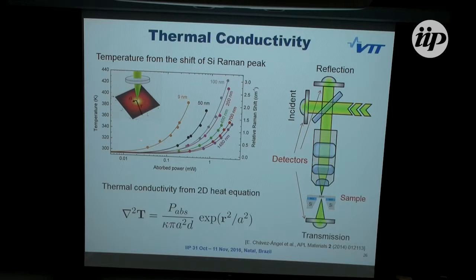So here are the measured curves. These are different thicknesses of membranes. When the absorbed power is increased, the temperature increases, so there's a shift of the Raman peak. And these curves can then be fitted with this 2D heat equation, where A is the spot size, R is the coordinate, and D is the thickness of the membrane. And this we know now, so we can calculate the kappa, the thermal conductivity.